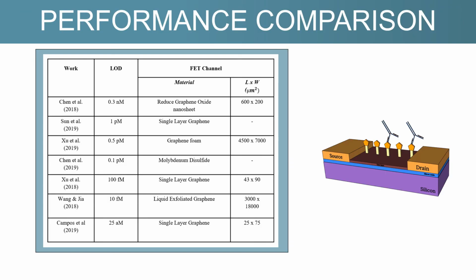To understand the effectiveness of the sensor, the performance comparison is observed based on the limit of detection. The choice of material and the design of the graphene, plus a smaller area of the channel, contribute to a lower LOD. This is mainly because of the higher transconductance. Based on Campos et al. 2019, they were able to achieve down to a 25 attomolar limit of detection with a single layer graphene at the channel and a smaller channel size.